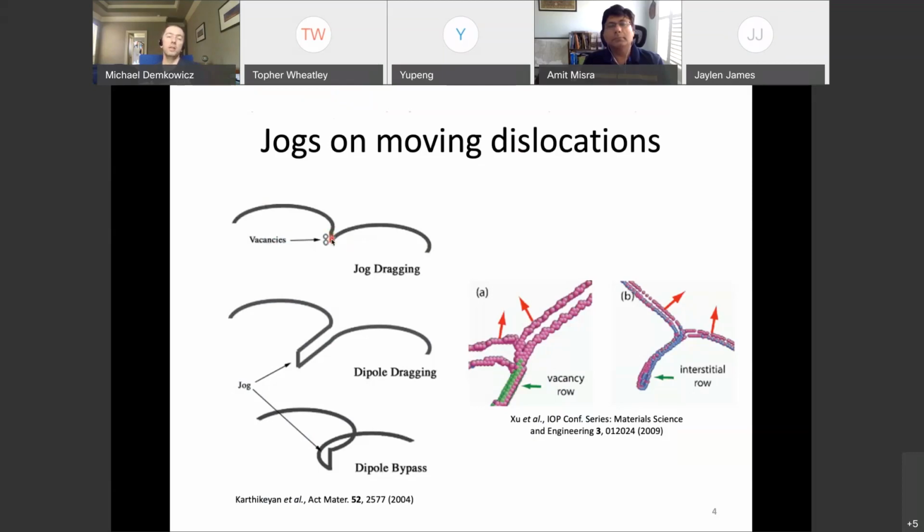So the dislocations are going to bow out of that jog. And if the force acting on the jog is high enough, then eventually it may become possible for that jog to get dragged along. As it becomes dragged along, it leaves behind point defects, in this case, vacancies. So this is something that you can conclude immediately just from knowing the geometry of this configuration.